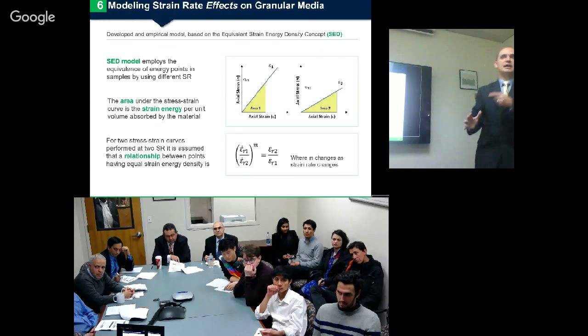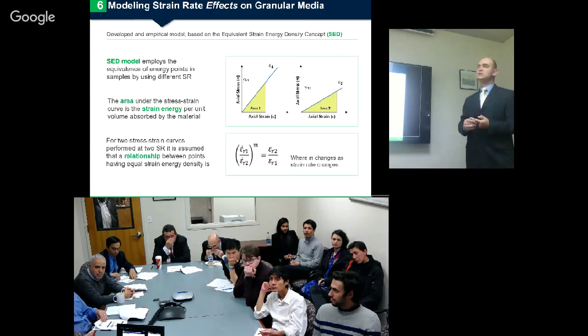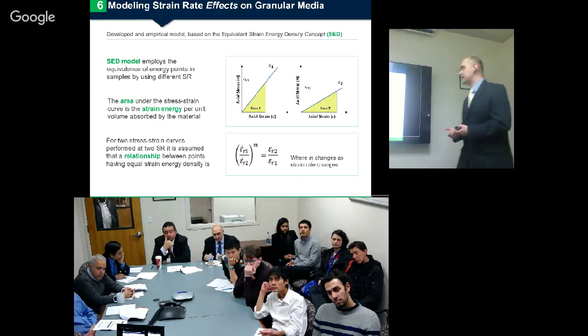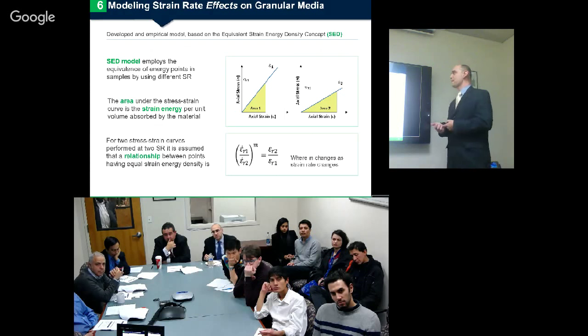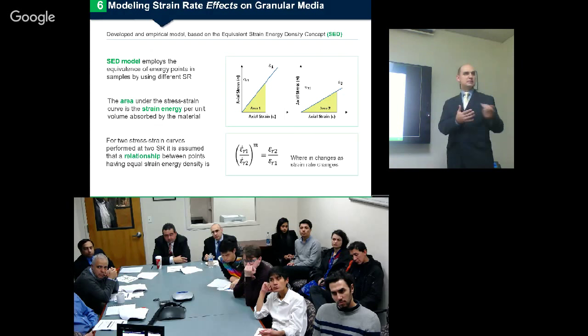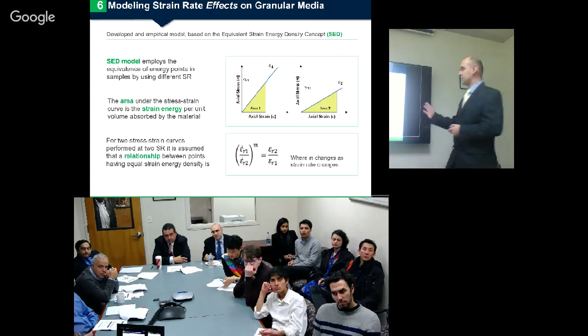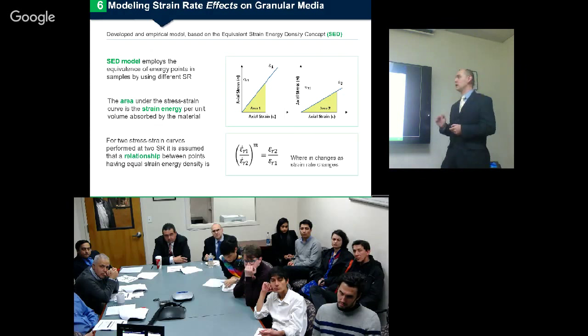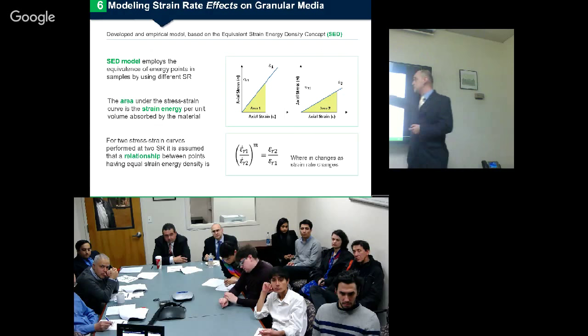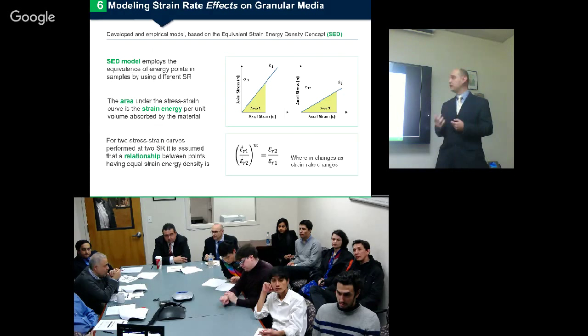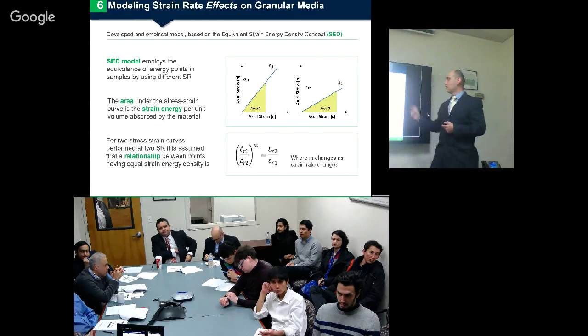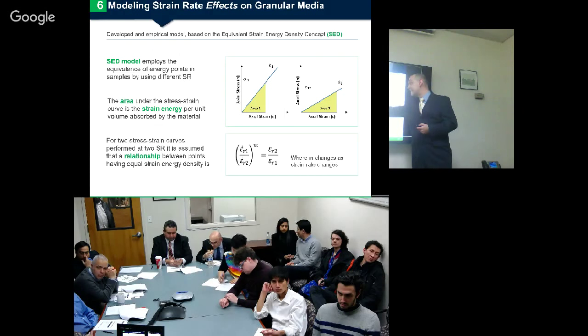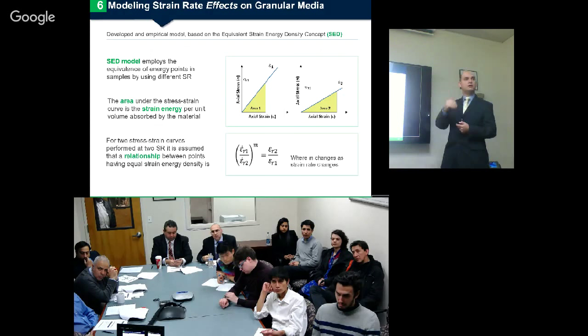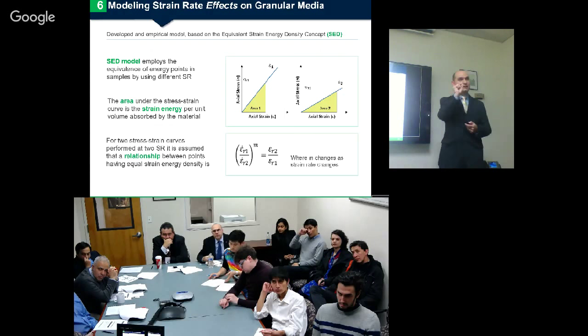Now, based on all of these experimental results, the idea was to develop an empirical model that is based on the equivalent strain energy density concept. This concept is very well known. It's been used in material science, in mechanical engineering, in civil engineering. What it says is that if I have two stress strain curves, same material, loaded at different strain rates, epsilon dot 1 and epsilon dot 2, there is some point where these two areas are equal. Obviously, this magnitude of the axial deformation is going to be less than this one, according to what we saw earlier with these loading stress strain curves. If these two areas are equal, what's going to be different is the axial deformation.